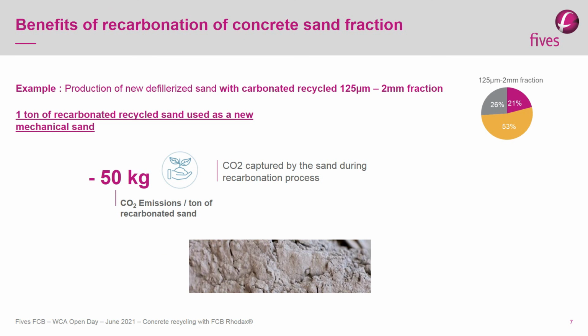A very interesting route for the sand fraction is to catch CO2 and transform the hydrated cement paste into calcium carbonate. We obtain a carbonated sand containing silica and limestone that can be used for both concrete and filler application. The industrial potential of CO2 capture is already about 50 kilos per ton of sand treated.